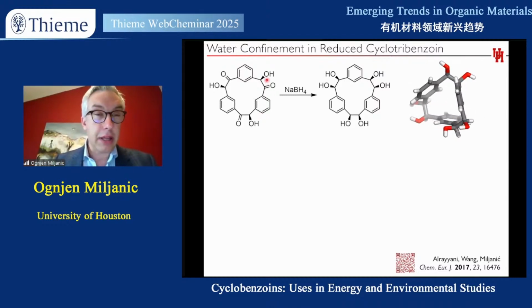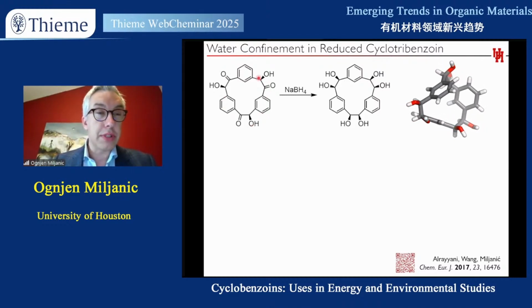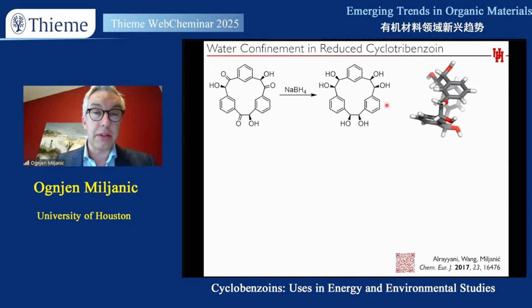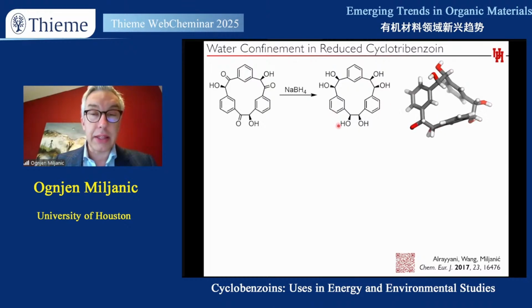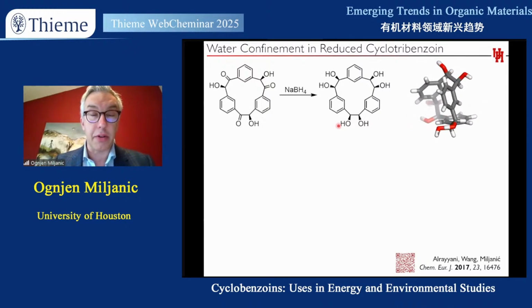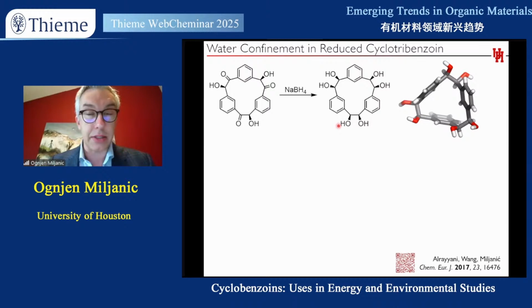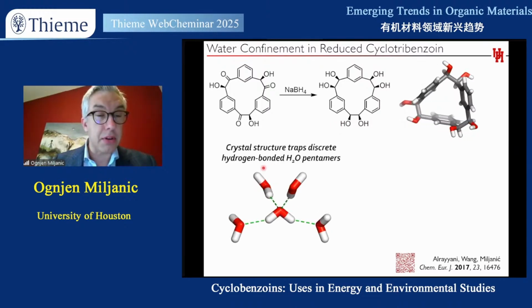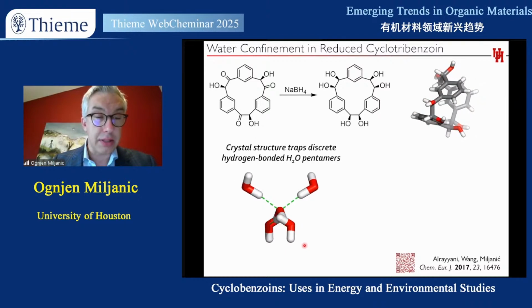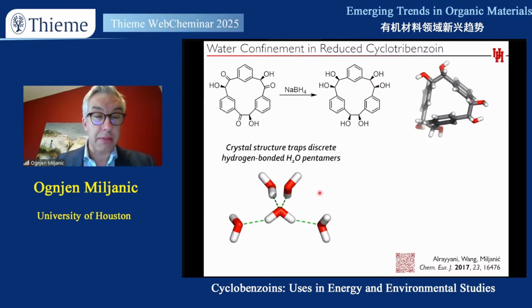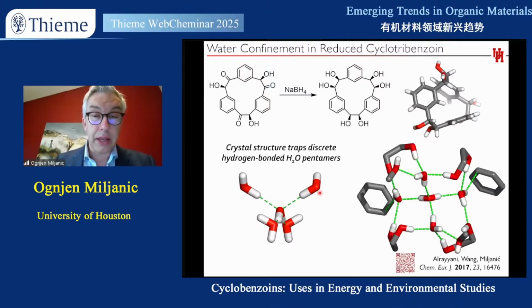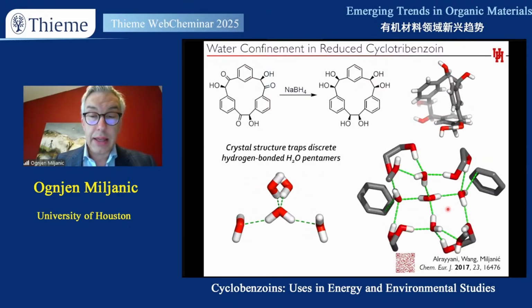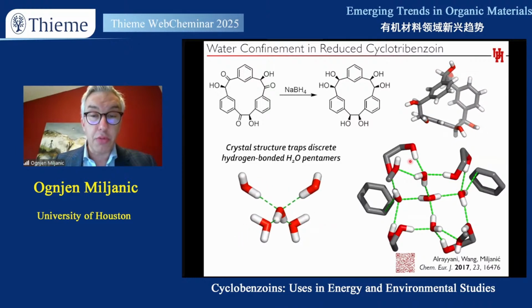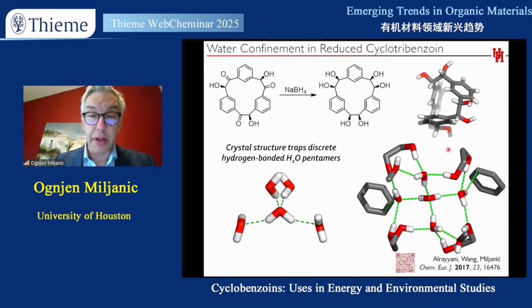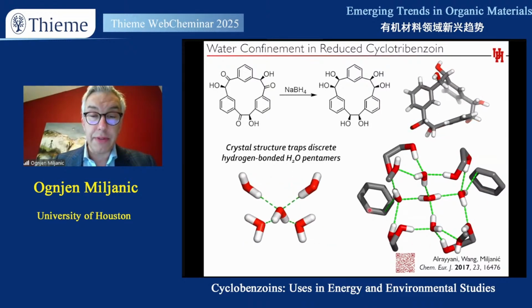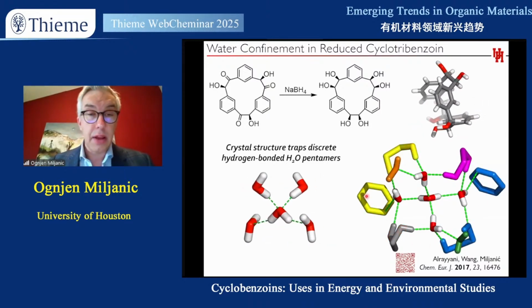The smaller molecule, we have managed to reduce this cyclotribenzoin into this hexol. This reduction is completely diastereoselective because of the cone-shaped molecular conformation, which then permits access of the reducing agent only from one side. Included here are these pentamers of water molecules, which are hydrogen bonded. We could identify all of the hydrogen atoms by crystallography here. And what is included here is really interaction of our pentamer with OH groups, as well as the benzene rings coming from 6 different molecules. And so what I'm showing you here is fragments of 6 different molecules. I'll show them now in different colors of our hexol.